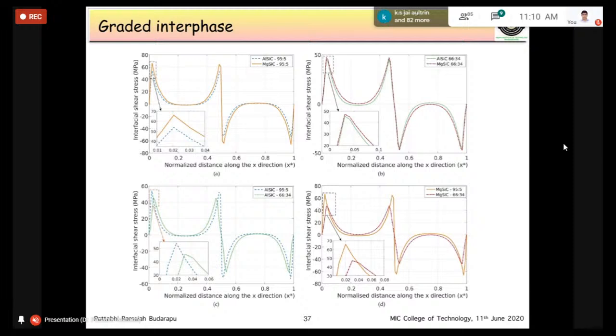In one of the cases, for instance, we could see some reduction in peak stresses particularly for this magnesium system. The peak stresses have been reduced from closely 66 or 67 to 45 or 46 megapascals. So yeah, 66 to 46, almost 20 megapascals reduction.